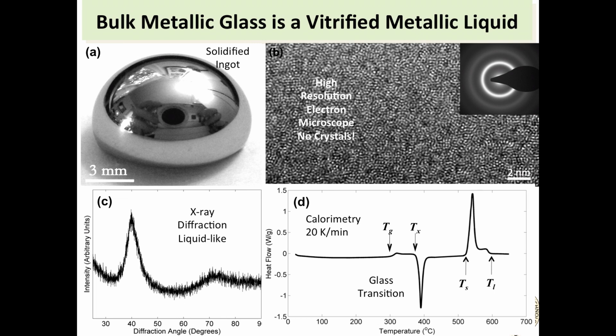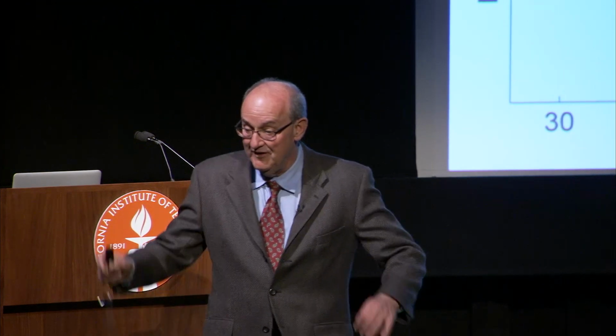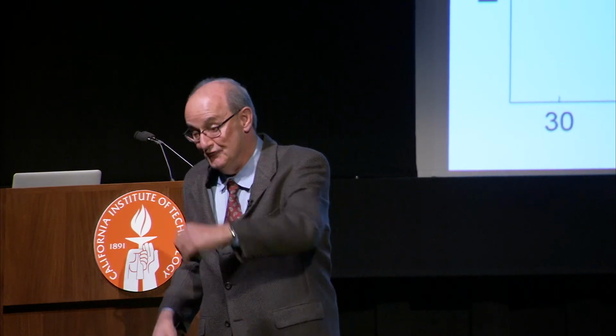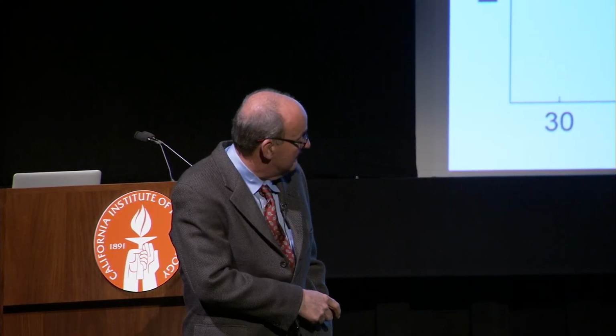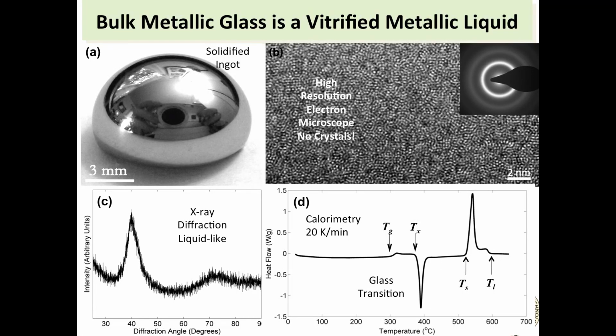And then if you keep heating it, suddenly it crystallizes. We hit the TTT, we hit the crystallization nose when we heated it up. And you take the crystallized material, you keep heating it, and it melts again, and so we made a glass. It's a big chunk of metallic glass.